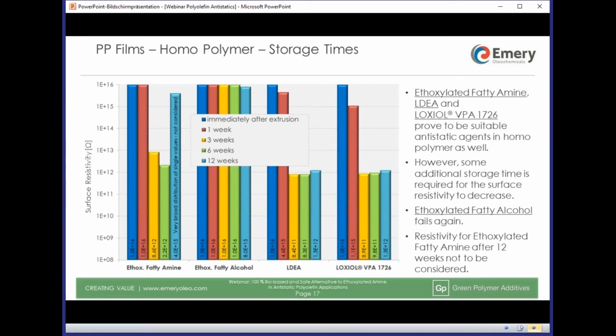PP film chart number 3, we are now in PP homopolymer, and again look at the surface resistivity at different storage times. You see for each product, the initial figures are very high. Only after 3 weeks storage, the resistivity is on a good level. If you recall the diagram 2 slides before, this was not the case for random copolymer PP. The reason is that homopolymer PP is more crystalline. That is why migration rate of the additive is reduced.